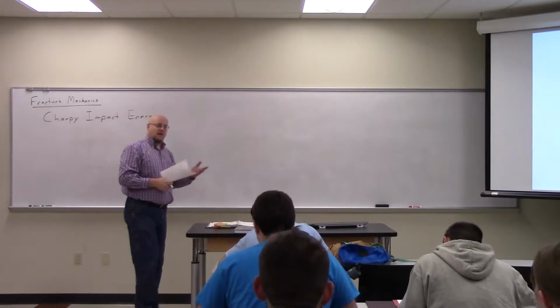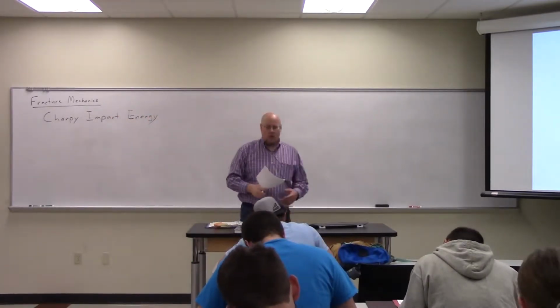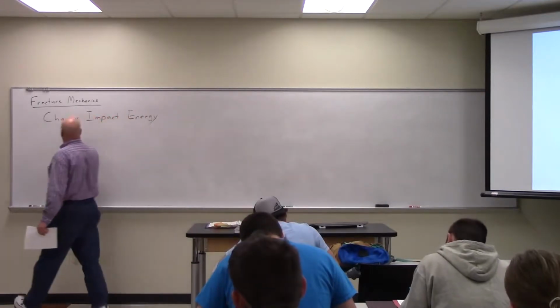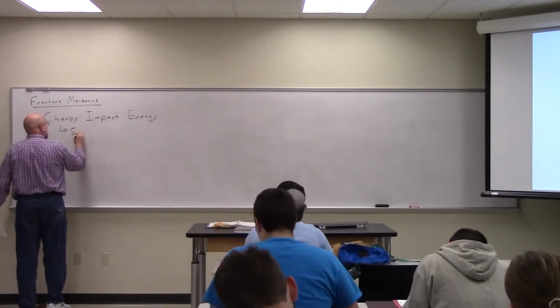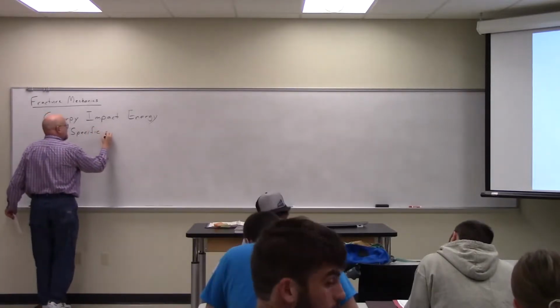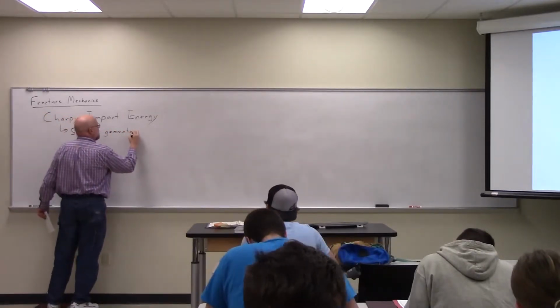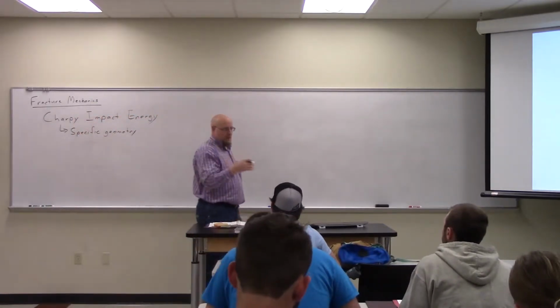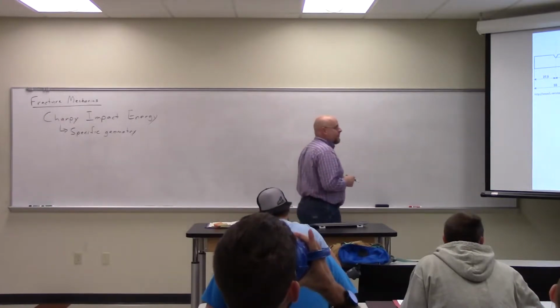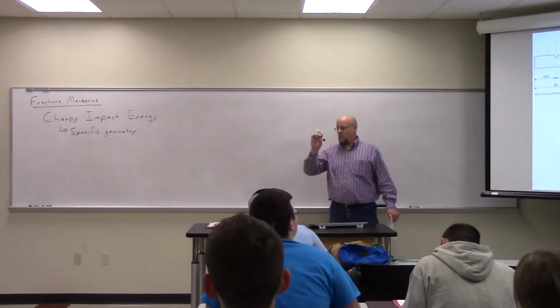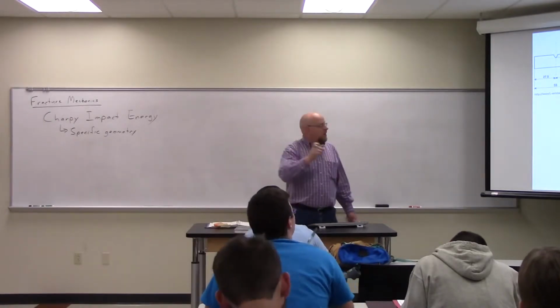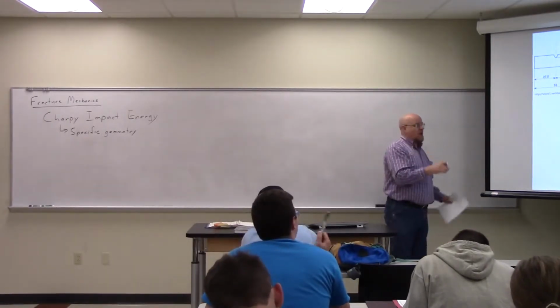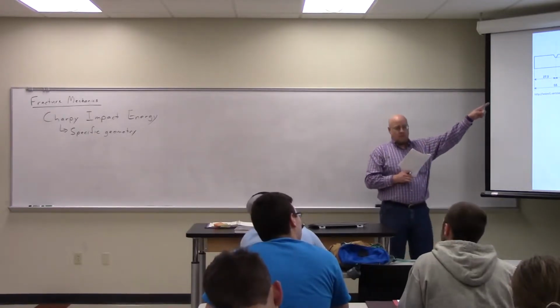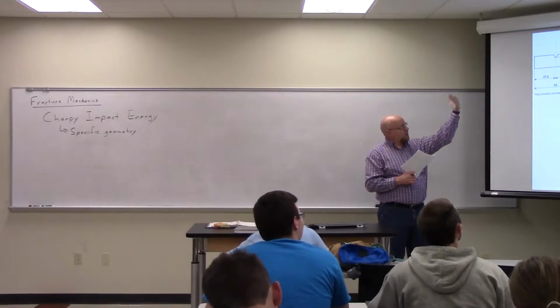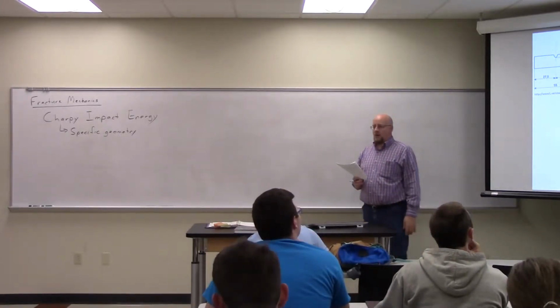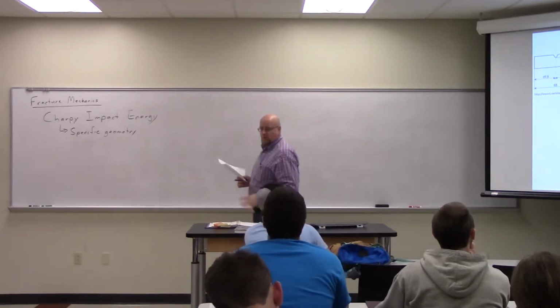Charpy impact energy is a mechanism for characterizing the fracture behavior of a material. So Charpy impact energy takes a specimen of a very specific geometry. Specific to the material or specific to the Charpy impact test? So there's the specimen. It is 10 millimeters square, so it's just a little one square centimeter bar, and 55 millimeters long. And then there's a V-notch cut in the top. You can see the distinction there. It's a 45-degree included angle and a radius of curvature of 0.25 millimeters. So it's a very specific geometrical arrangement for this sample.